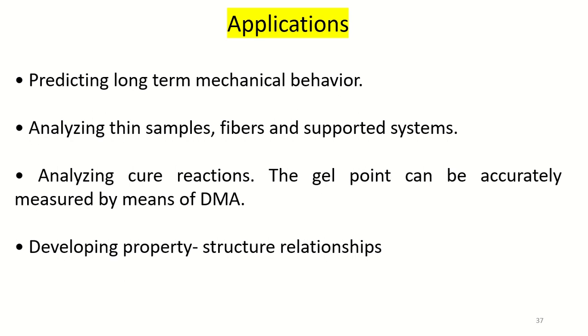For non self standing samples, it is possible to use a support material. The support should show a constant storage modulus throughout the experiment and a very low loss modulus. Some classical forms of support include a wire mesh or a thin glass plate. The next one is analyzing cure reactions. The gel point can be accurately measured by means of dynamic mechanical analysis. The value that is reported for the gel point is the time at which the storage modulus equals the loss modulus, and we have already studied that. It is relatively independent of the frequency.